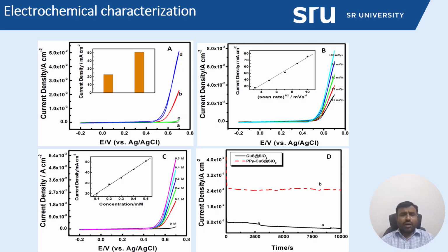In order to verify the catalytic performance of the as-fabricated polypyrrole-coated copper sulfide hollow sphere, we have performed different scan rates from 10 up to 100 millivolts per second. What happens when increasing the scan rate is that the oxidation peak current also gradually increases. This indicates that the copper sulfide coated glassy carbon electrode has high electrocatalytic characteristics towards the electrooxidation of methanol in extreme conditions, from low to high scan rate, without any deviation of the oxidation peak or suppression of the oxidation peak current, because only a high performance catalyst can provide this characteristic.